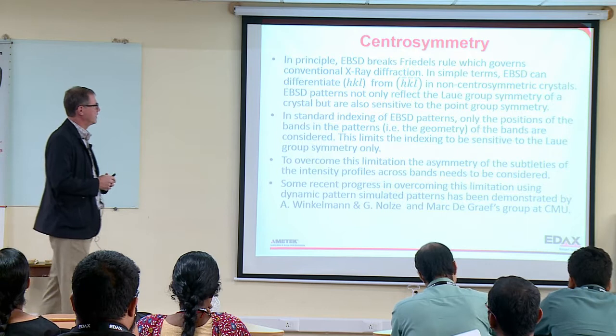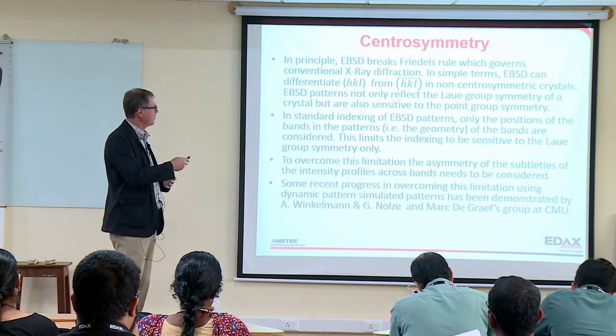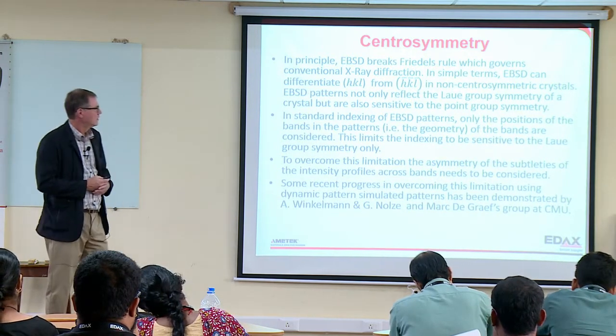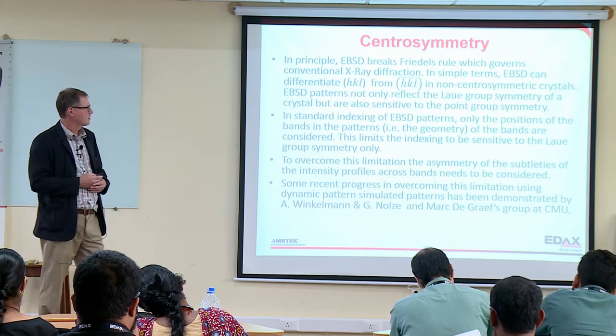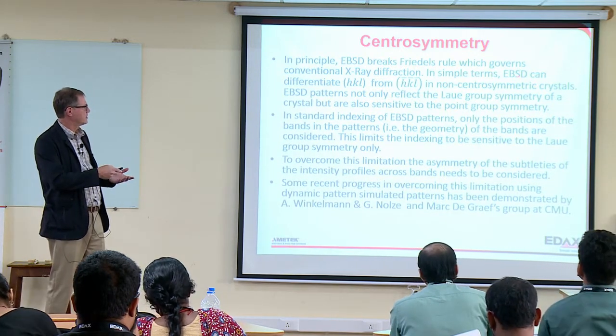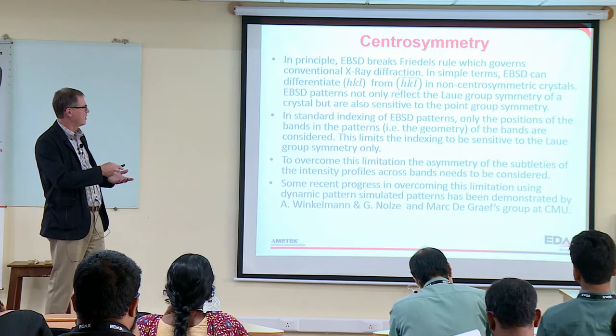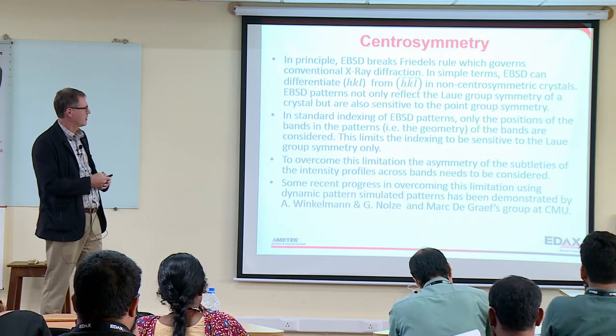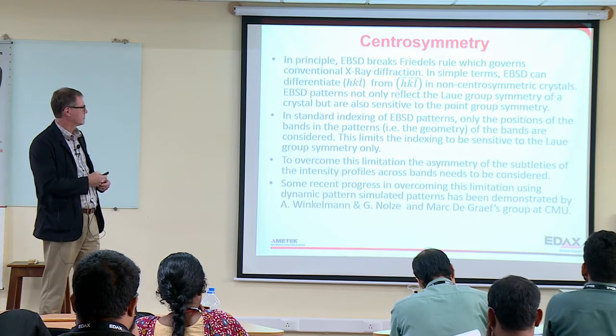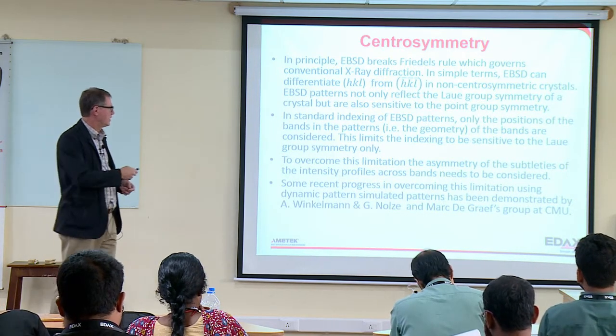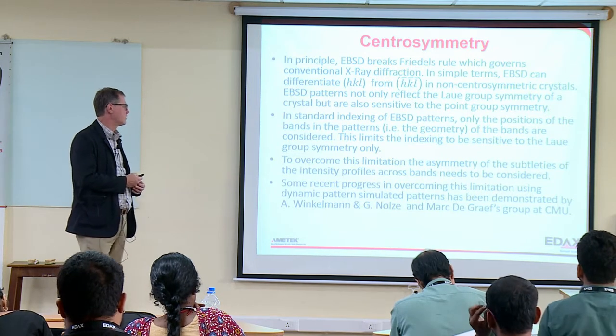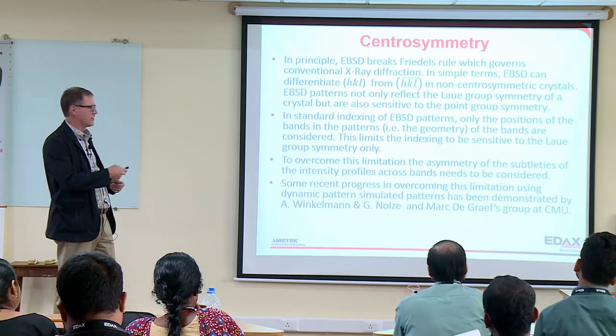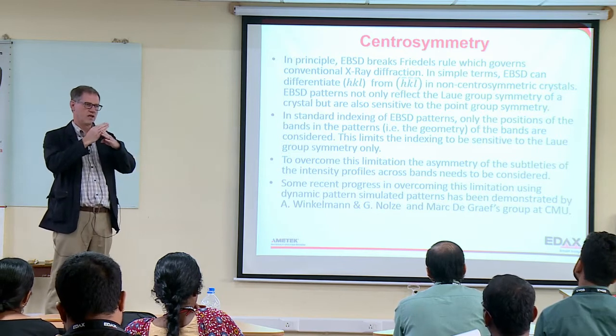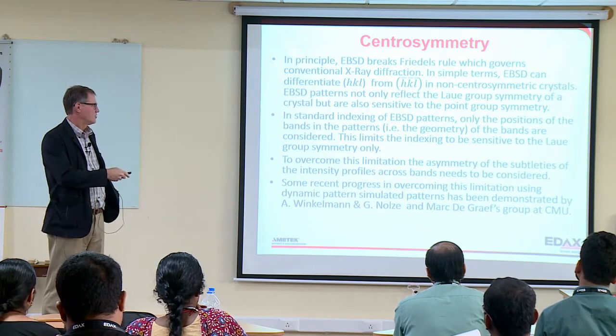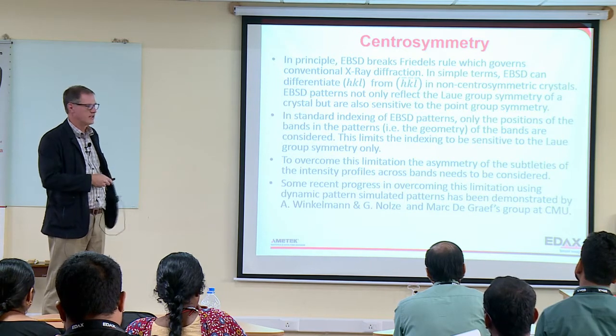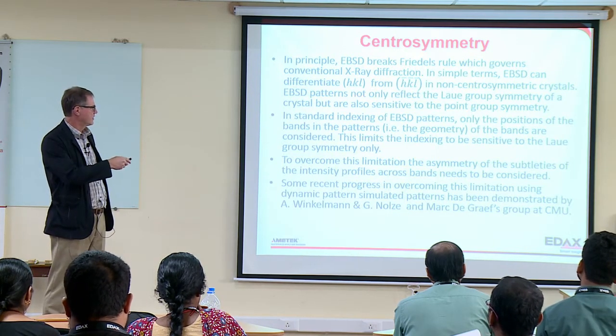And this brings me to the idea of centrosymmetry. So in theory, EBSD breaks Friedel's rule, which governs X-ray diffraction. So in simple terms, it means in EBSD, we should be able to differentiate HKL from H minus K minus L in non-centrosymmetric crystals. But in standard indexing of EBSD patterns, we only look at the positions of the bands in the patterns. We're only looking at where this band appears in the pattern. So that's the geometry. We don't consider the intensities, and it's the intensities that differentiate these two.